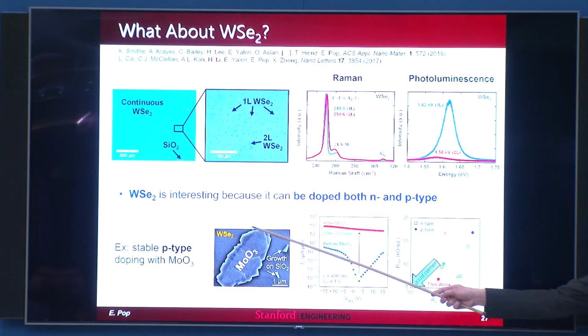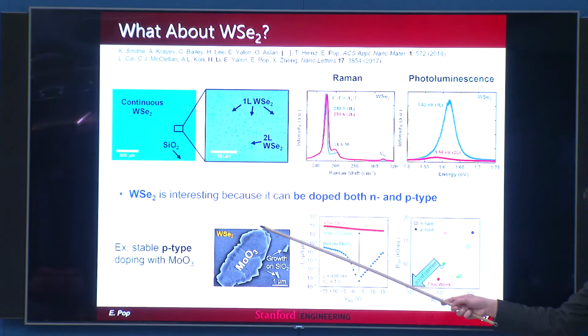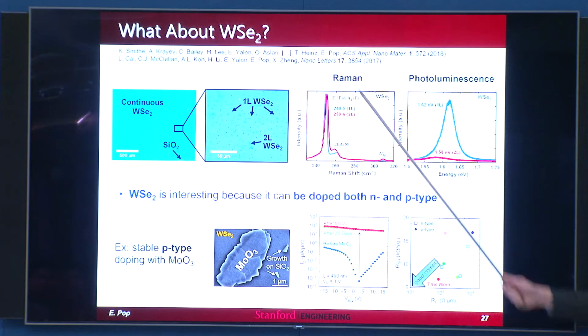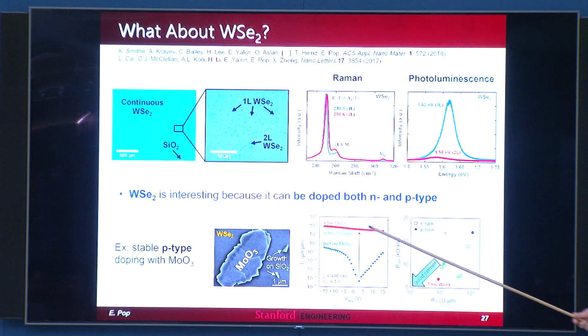P-type is done using moly oxide on top. And this is actually a beautiful crystal of moly oxide grown directly on top of WSe2. This is done with Xiaolin Zheng's group at Stanford. And it's quite a stable doping as well, and it's P-type, and it gives pretty good hole doping for these materials. So this is what we're doing with WSe2 at the moment.